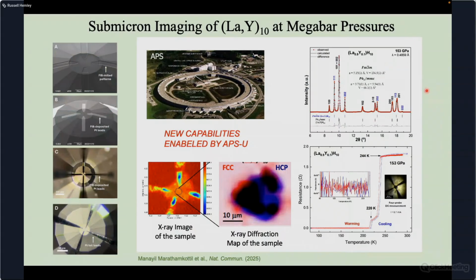So we did resistance measurements using various kinds of techniques shown here. In fact, in particular, the one at the bottom. And as I described in the first studies, we did a combination of conductivity measurements and X-ray measurements. But now we can map in great detail with 1 micron resolution the structures that emerge. First of all, we have beautiful diffraction data now that we can take at quite high pressure. This is 150 GPa, somewhat lower than what was required for pure lanthanum. Beautiful patterns that we can refine.